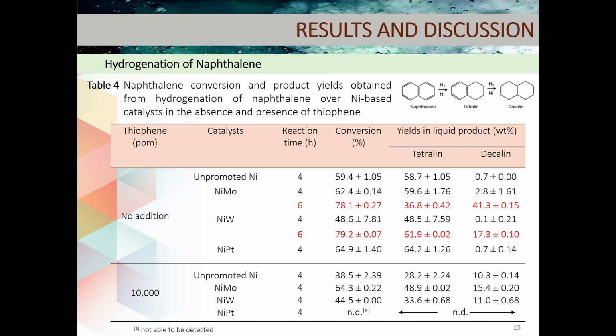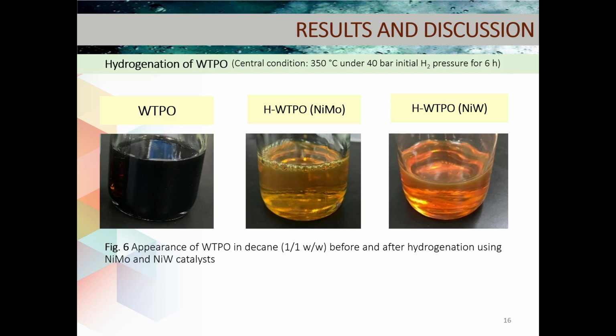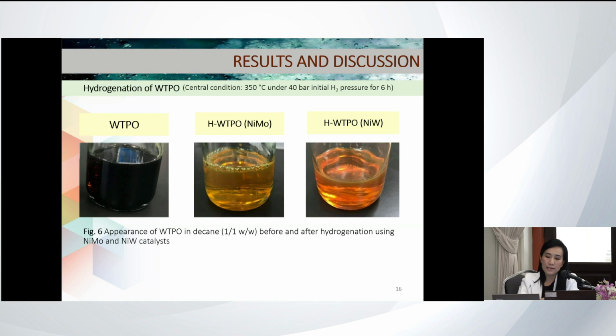60%. But in the presence of sulfur, where we add thiophene into the reaction mixture, you can observe that the nickel platinum and the unpromoted nickel are not effective at hydrogenating the naphthalene, and it means that the nickel platinum and the unpromoted nickel have a low resistance to the thiophene compound. And for the nickel, from the previous part, we use the nickel tungsten and nickel molybdenum as the catalyst for the WTPO hydrogenation. And you can observe that the color of the WTPO changed from black to yellow. It means that the unsaturated structure is removed to get a more saturated structure.